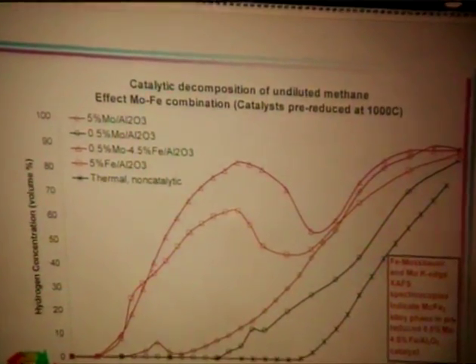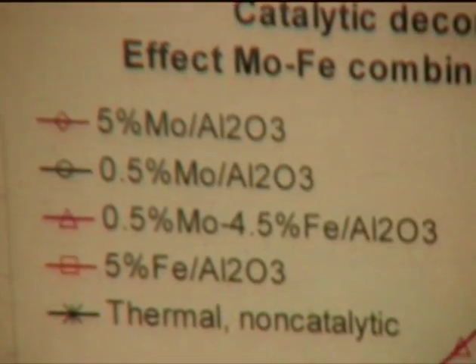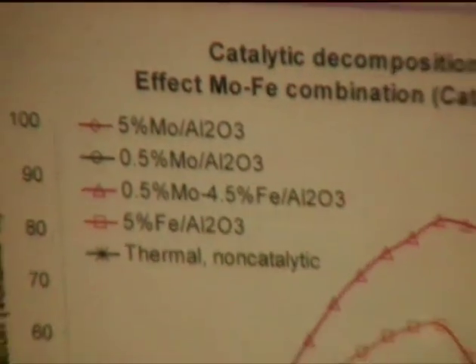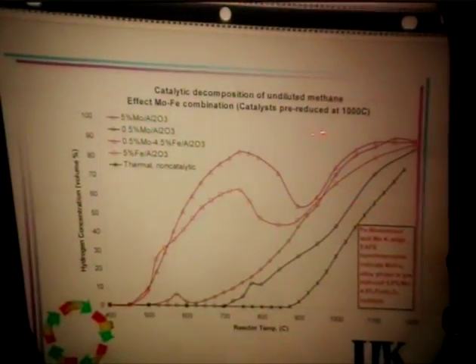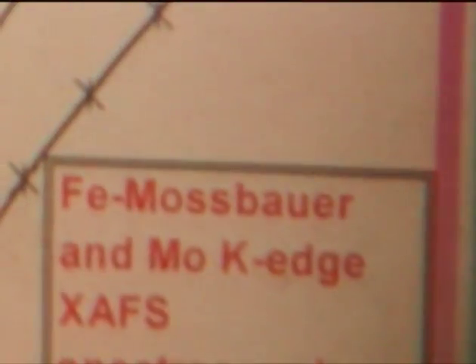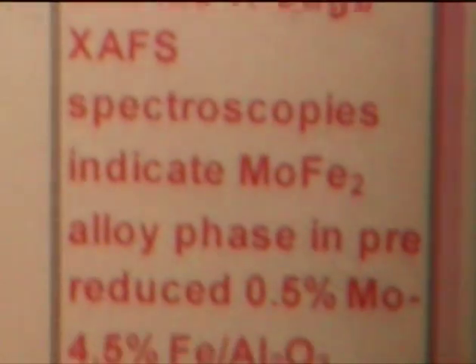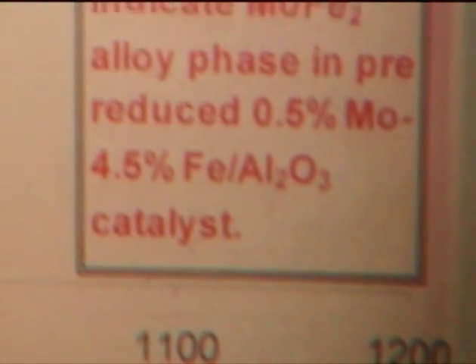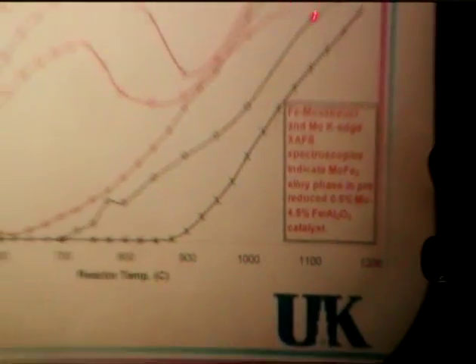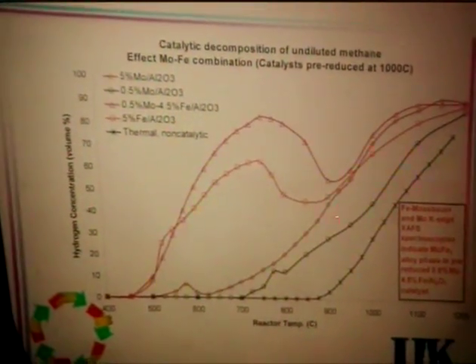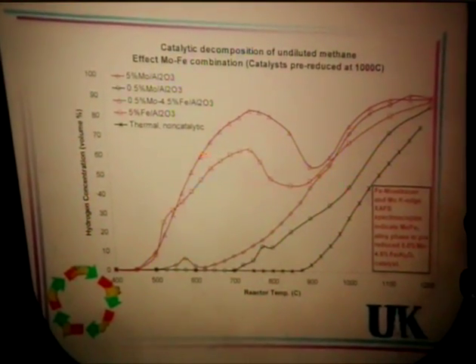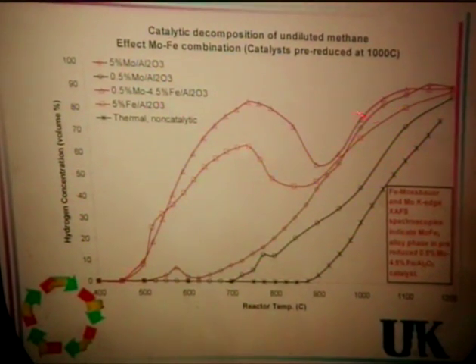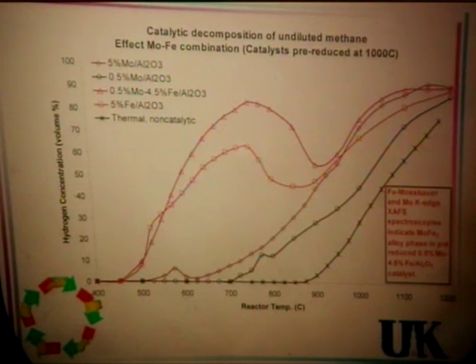Here we have used the moly and iron combined binary catalyst as well as mono moly and iron catalysts. Here is the non-catalytic cracking, and here is the 0.5% moly on alumina, the black curve. This one is 5% moly on alumina, and this one is 5% iron on alumina. All these catalysts were pre-reduced at 1000 C.